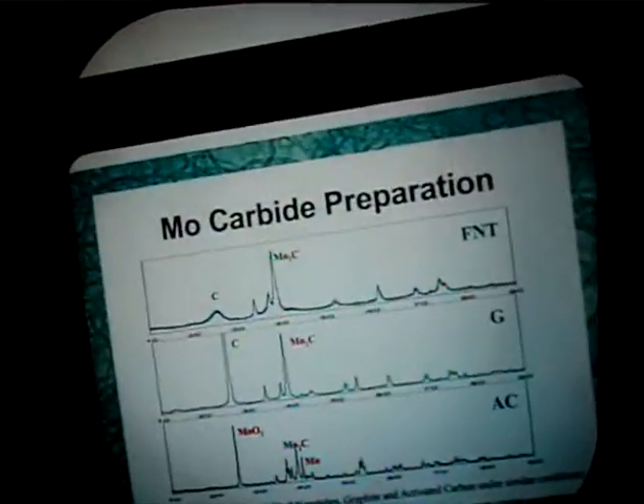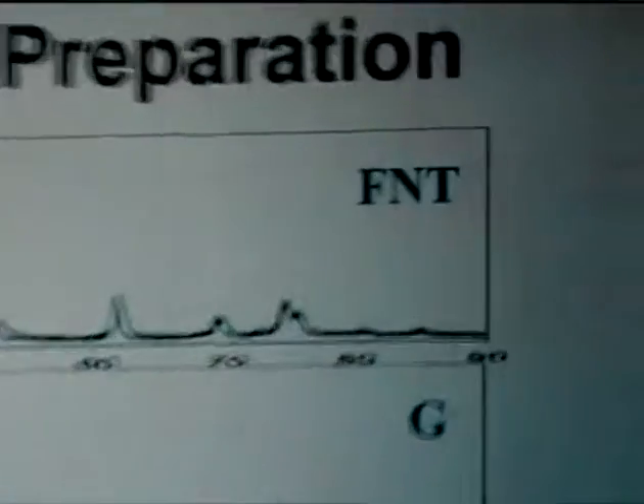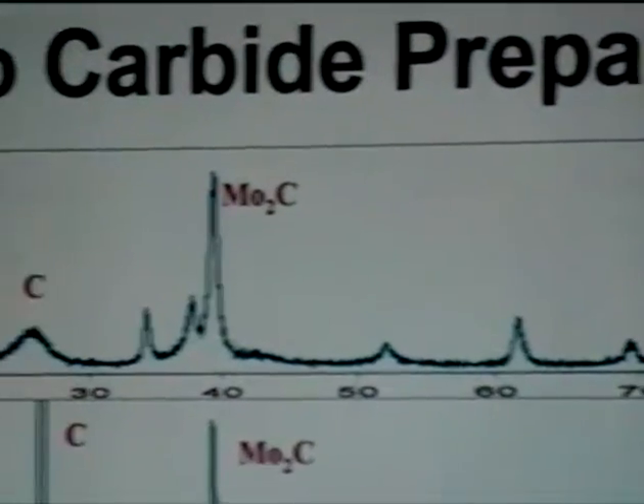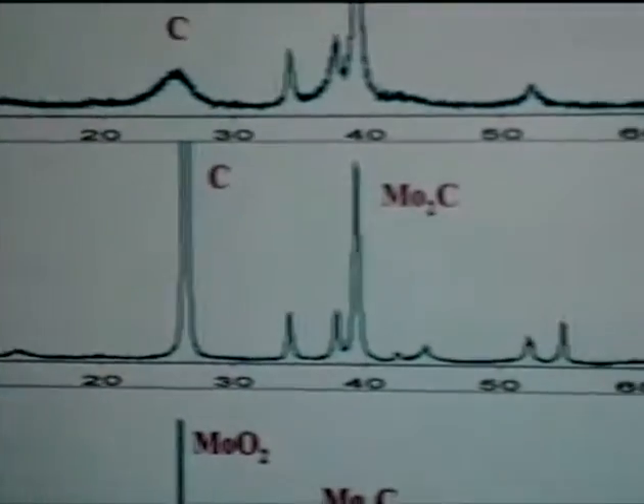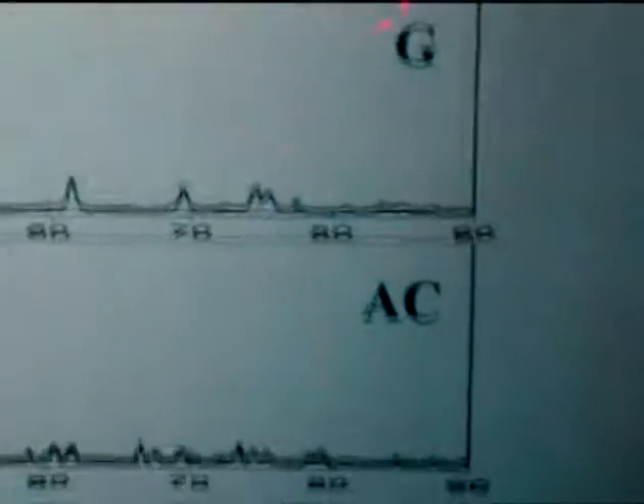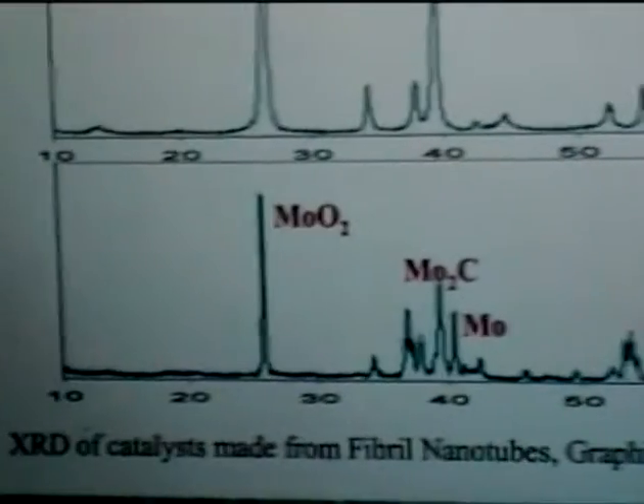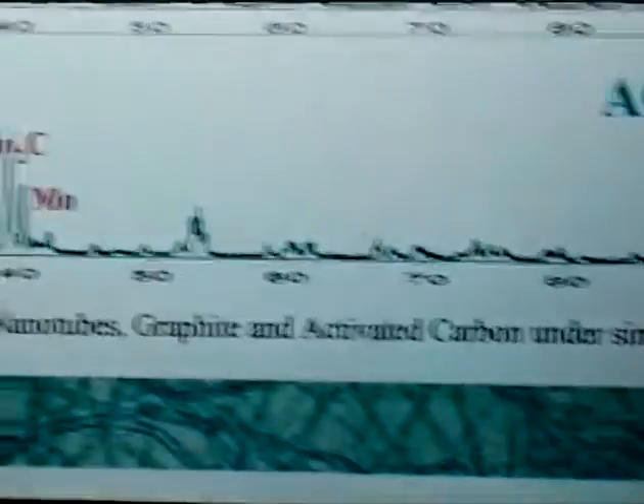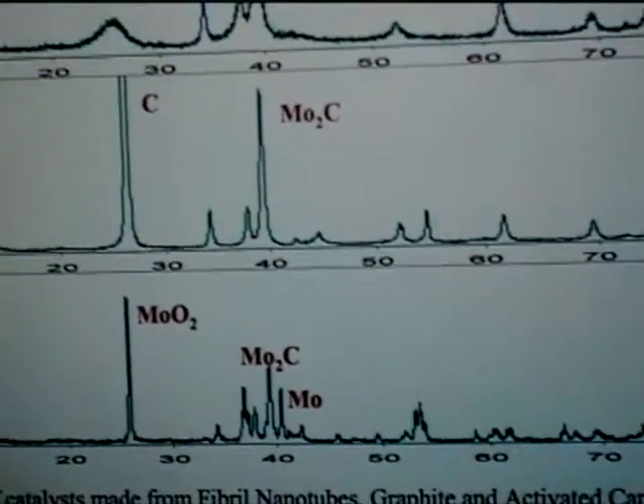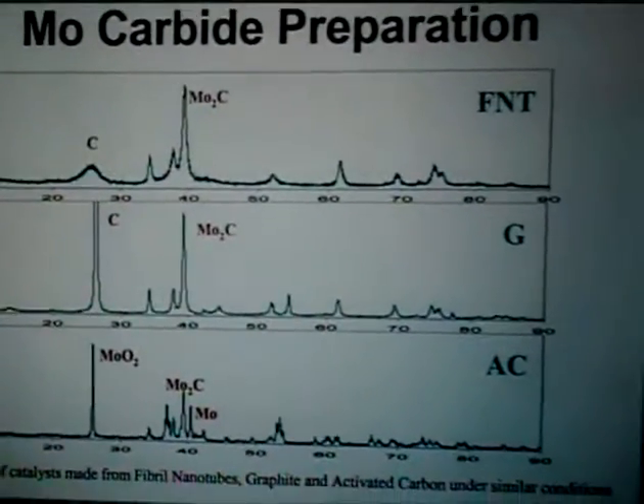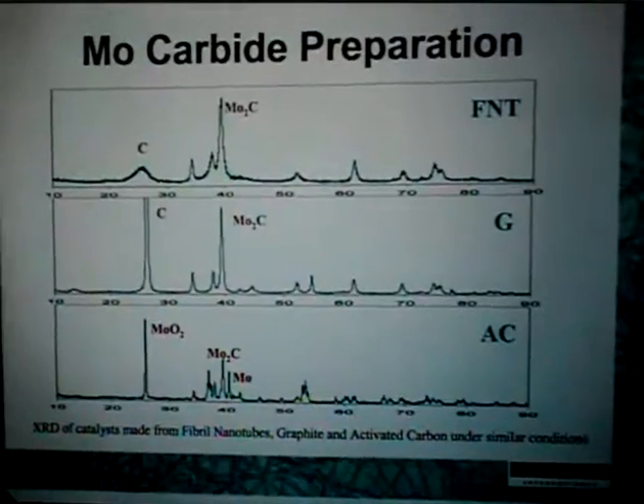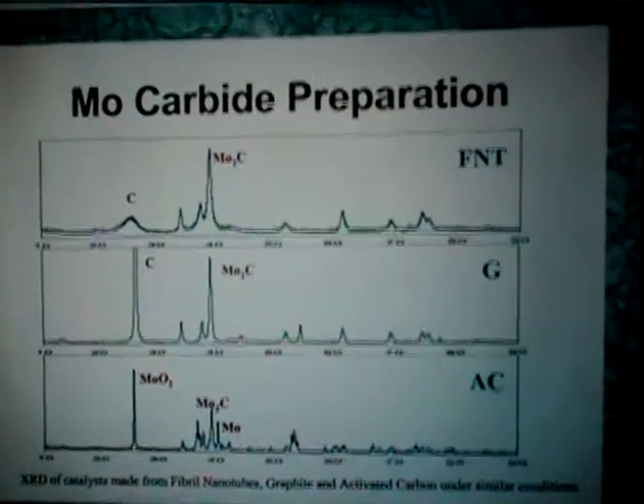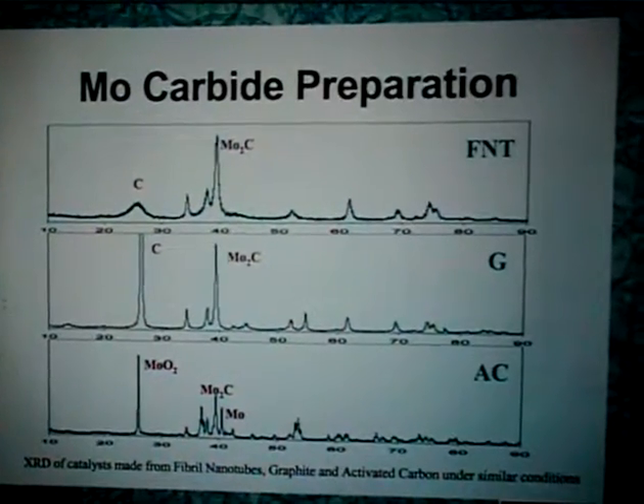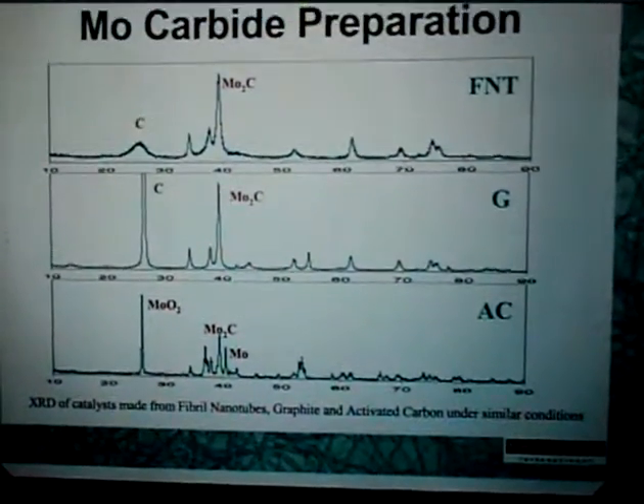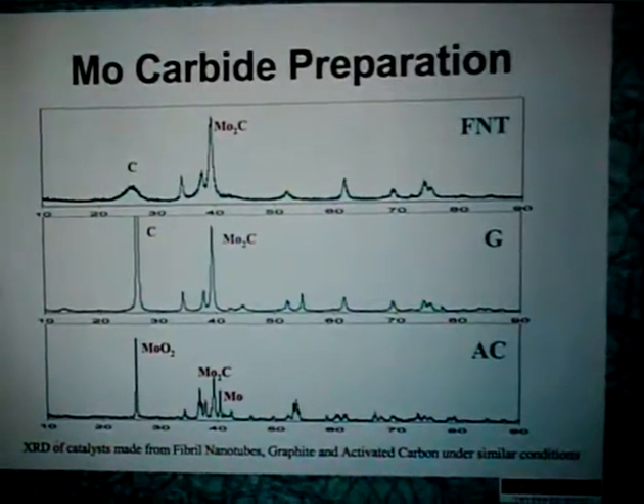So let's start with the characterization results, and we have three different types of carbon: the fibril nanotube, the graphite, and the activated carbon. Now, the way that those catalysts were prepared, they were mixed with molybdenum trioxide, and we made a physical mixture between those compounds, and then they're heated at high temperature, and that drives the molybdenum oxide in direct contact with the carbon to be transformed into molybdenum carbide.